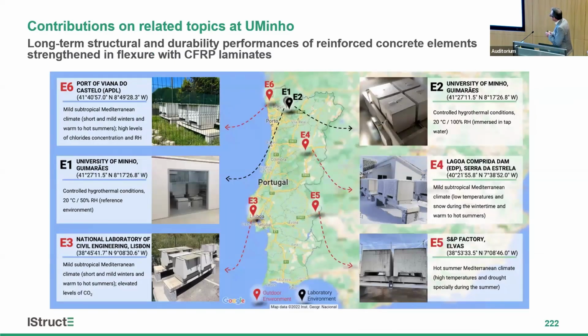To finalize, I'd like to also show that we are studying not only short-term, but also long-term, and durability and long-term is an issue. And what we have done was creating several experimental stations indoor in our lab and outdoor in different places of Portugal, including where we also have snow in Portugal a few times per year, not too much. But in reality, the idea here is to compare the accelerated aging tests that we do at the lab with natural aging, okay? We do this at material, bond, and full-scale level.